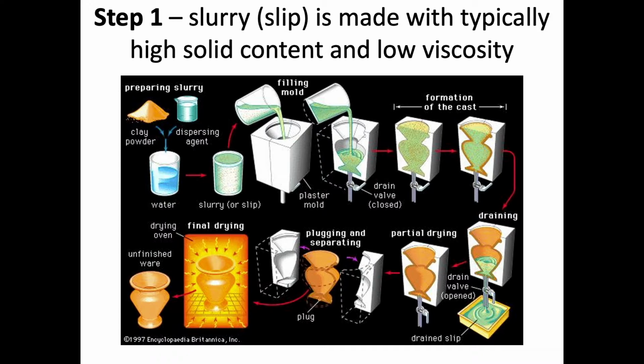All right. So again, let me walk you through the steps, and I found this nice demonstration of the various steps that have to be undergone to do the slip casting. But the first step is we have to actually prepare the slip or the slurry. And so typically what we try to do is maintain a pretty high solid content. So we want mostly our ceramic powder and not a lot of liquid to have to remove. But we do want to also have low viscosity. So we want it to be free flowing as well. So we don't want it super thick in colloquial terms. So that's the first step.